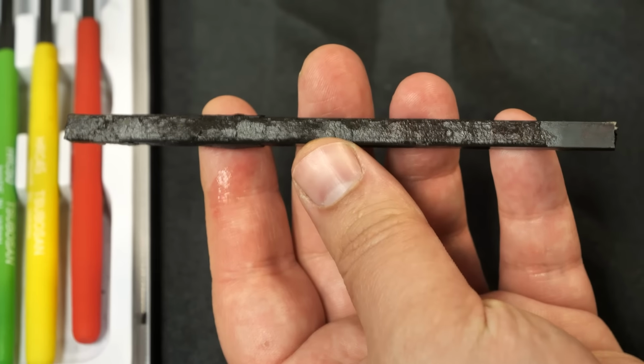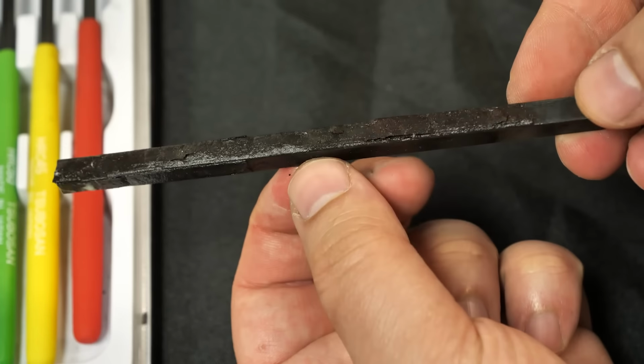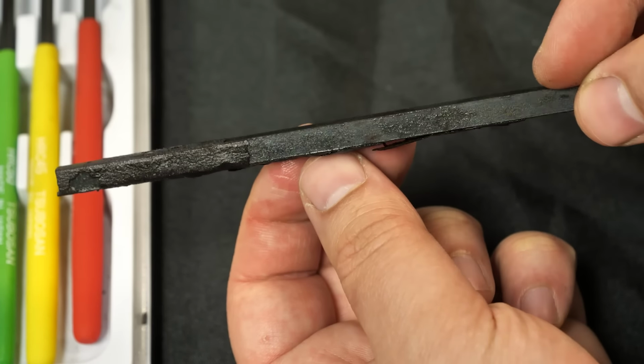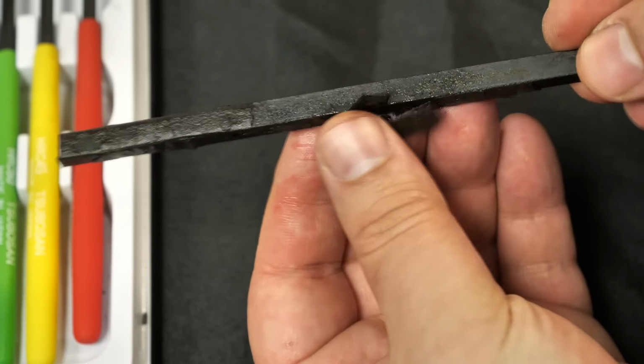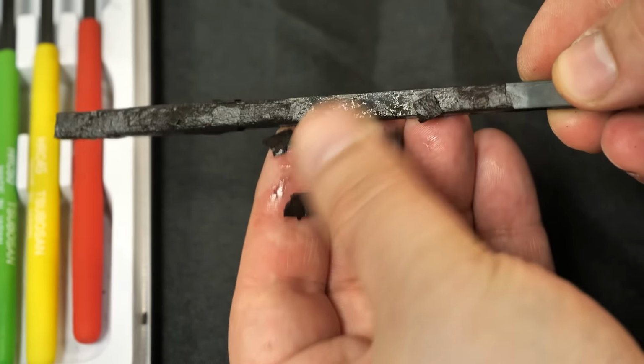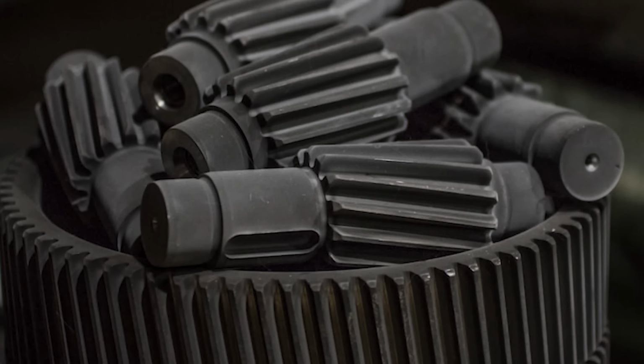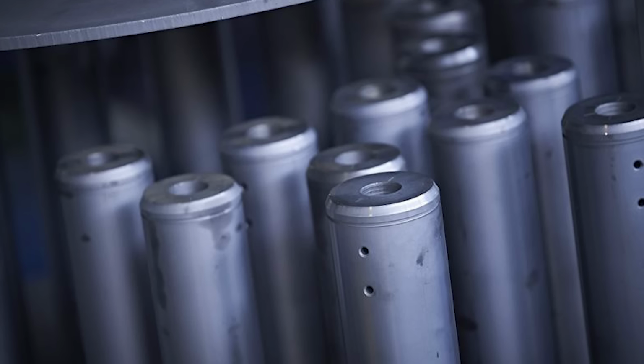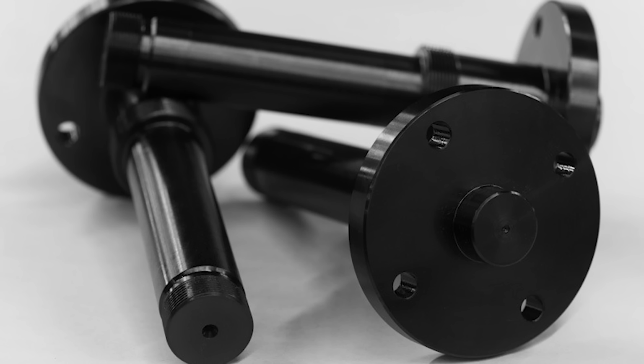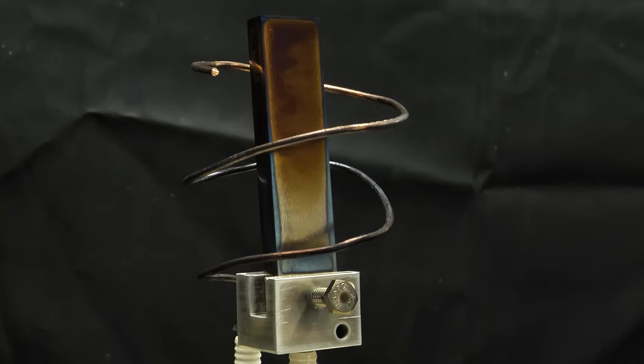Speaking of surface finish, you can see why the plasma treatment might be preferred, or at the very least using the cyanide salts, which would mar the surface less. The surface straight out of the salt isn't the prettiest. With plasma nitrided parts, the surface comes out glossy and nice, and at the end of the process you can change out the reactive gas for oxygen to blacken the surface and build a tough oxide to help prevent further rusting. But with that, we've covered all the DIY ways to turn iron into usable steel.